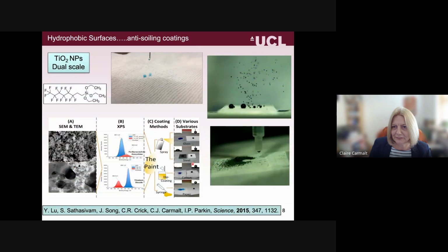So where we started with this was a number of years ago, looking at titanium dioxide. We took some dual scale nanoparticles, so some very small nanoparticles and some larger ones. We mixed those up in ethanol, and then we added this perfluoroalkyl silane, which is there to help provide the low energy surface that's required. In the video that was running, I think I have to turn my laser pointer off to get the videos to run. What we've done here is taken that paint and put it onto actually just blue tissue that you get in a lot of laboratories, let it dry, and you can see now the water doesn't absorb at all into the tissue. It's completely just rolling across the surface.